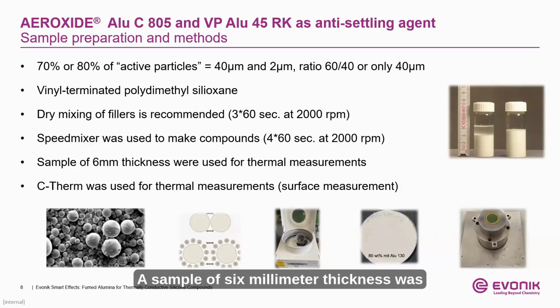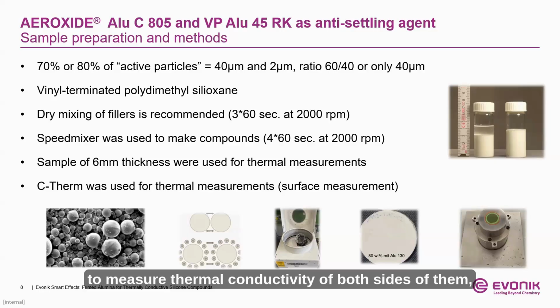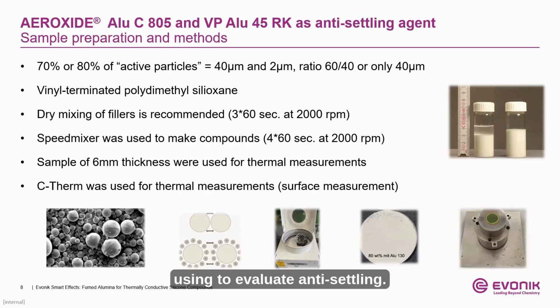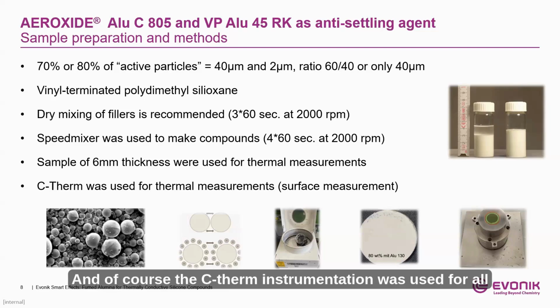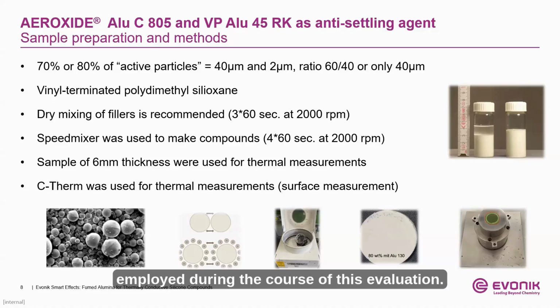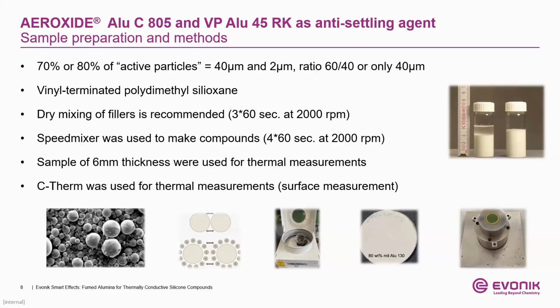A sample of 6 millimeter thickness was used for the thermal conductivity measurements. If you look to the images below, the first image from the right is basically what we're referring to. It's this little, we'll call it a puck of material of the cured silicone on a 6 millimeter thickness to measure thermal conductivity of both sides of the material to evaluate anti-settling. We'll take a look at that in a bit. And of course, the C-Therm instrumentation was used for all these surface thermal conductivity measurements we employed during the course of this evaluation.